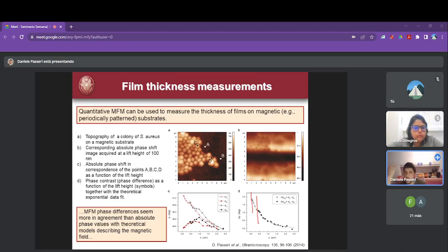Okay, in this case we could measure the height of the film because we had these edges. But imagine you don't have this edge, but you have a uniform film. From a graph like this, you can calculate the thickness of your film. Just something you should note is that somehow the differences between phases seem more in agreement with the theoretical model. Here, sorry, I didn't mention it. This dotted line is the theoretical model. It's an exponential decay. So the phase difference seems better than the absolute value of the phases.